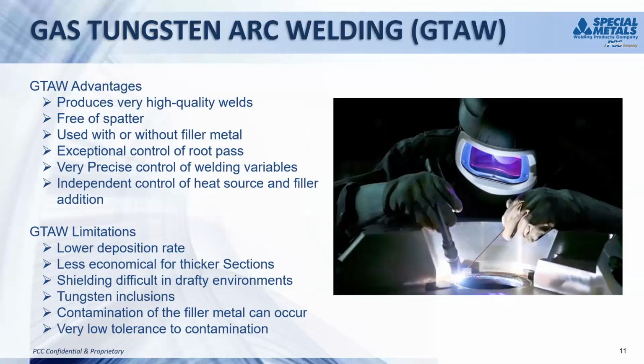So gas tungsten arc welding is probably one of the most preferred welding processes from a mechanical standpoint with nickel alloys. It has the advantages of very pretty, very high quality welds, very minimal spatter. You've got one of the few advantages where you can do an autogenous weld, which is no filler metal, or you can add filler metals in multiple ways, whether it's manually dipping the filler metal into the puddle, or we can set up a wire feeder to feed wire in at a very controlled rate, which does help increase the productivity and the deposition a little bit, but there's some nuances to work with that.